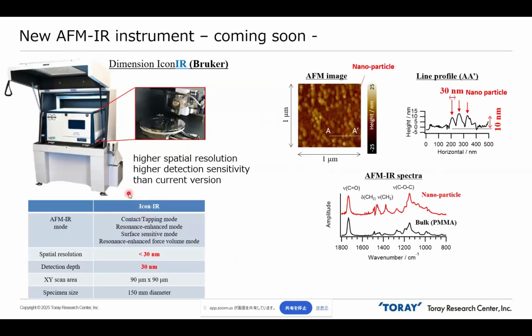But our new AFM-IR experimental system has better spatial resolution, below 30 nanometers. So I believe we can get information about the thin interfacial layer.